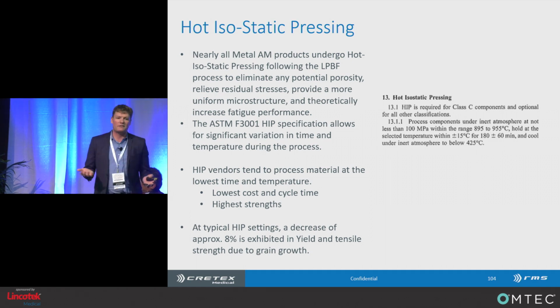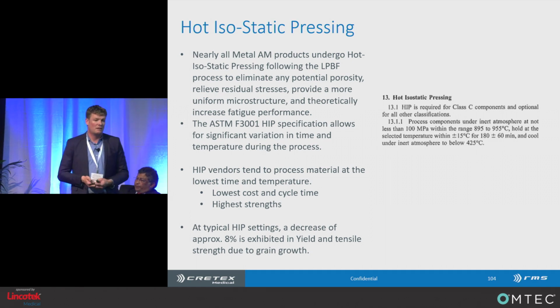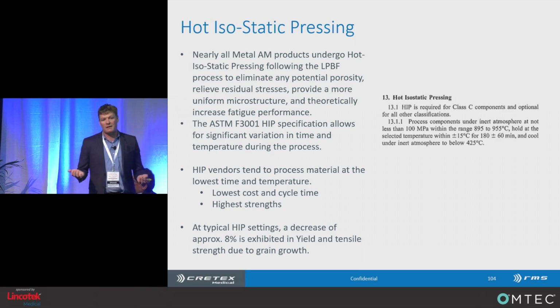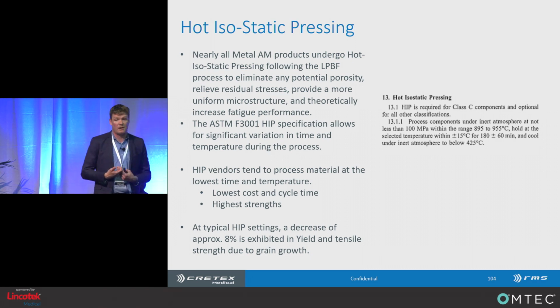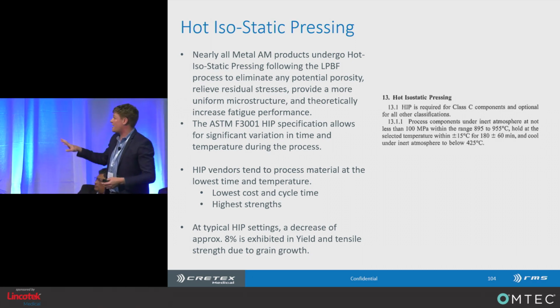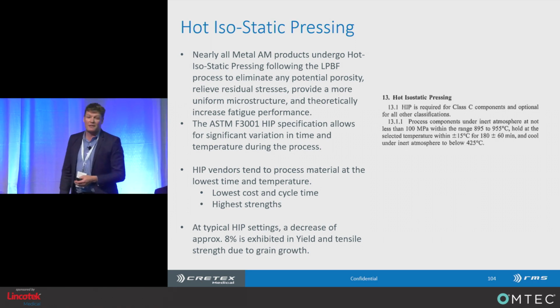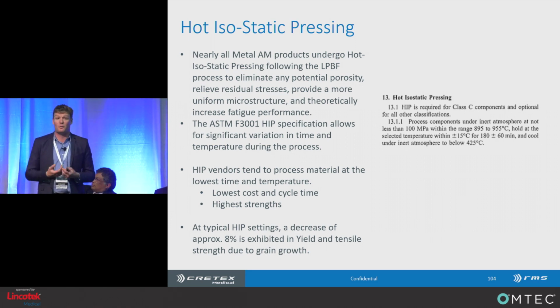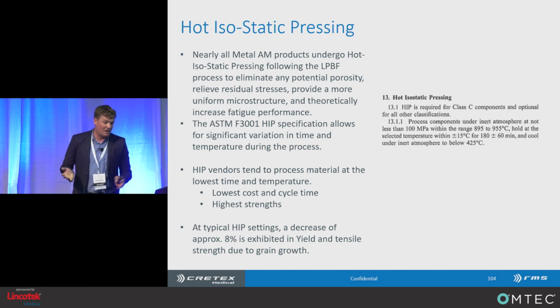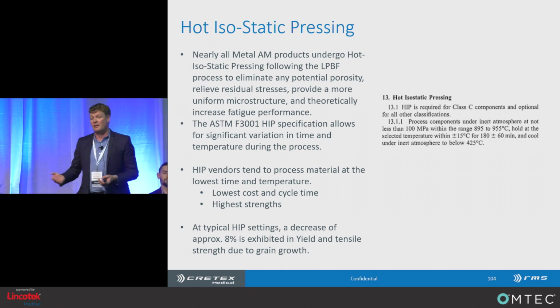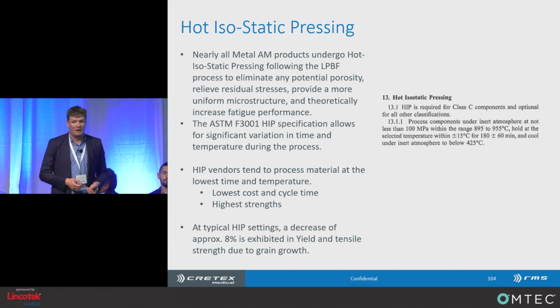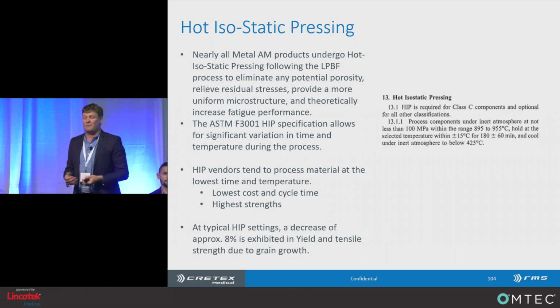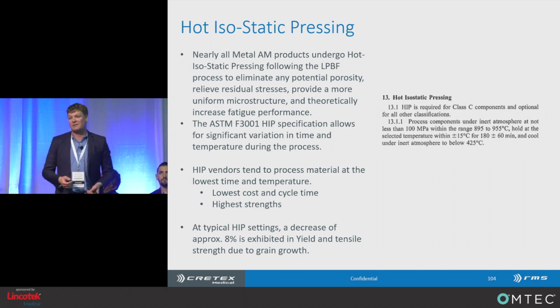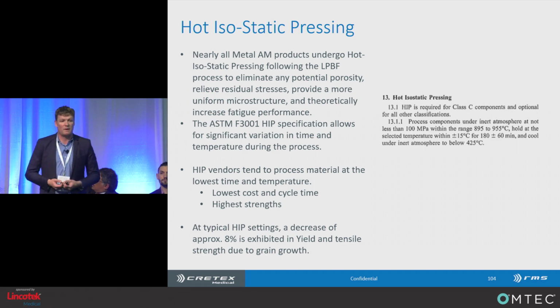One of the predominant ways that we do that is hot isostatic pressing today. I would say the vast majority of the products we make undergo hot isostatic pressing. You look at the specification for hipping in ASTM F3001, it's a pretty large window, right? It allows for anywhere from 2 to 4 hours in the hip furnace, and you can vary the temperature by 100 degrees, right? In practicality, the hip vendors want to make as much money as they can, so they typically do it at the lowest temperature for the shortest amount of time, so that their expenditures are less, right?